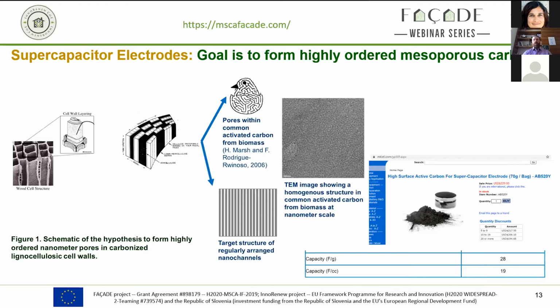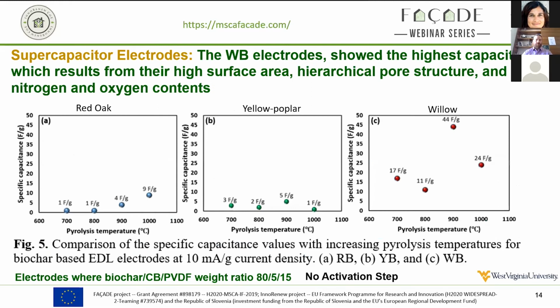So you'll start seeing how that compares to some of the work we're doing. The idea is that you first remove the hemicellulose through carbonization, and then you want to do the removal of the cellulose in a certain manner that you don't degrade the original biomass cellular structure. So you want to keep these really nice ordered channels, and you don't want to just blow it completely apart. I'll show you two examples with the same species, one where it's just kind of messy, and the other where you get nice ordered material.